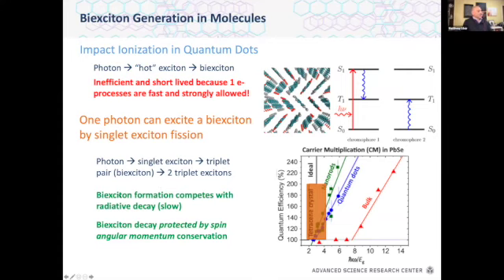So here, instead of Biexciton formation having to compete with carrier cooling, it has to only compete with some sort of decay back to the ground state. And so we're photoexciting a cooled singlet exciton. So again, carrier cooling, it's already cooled in the sense of it's not easily able to relax to any low-lying triplet level. So, we'll have 1 nanosecond or 10 nanosecond decay times back to the ground state. And so we have basically 4 orders of magnitude longer to form our Biexcitons. And in addition, what we'll see is that the Biexciton decay is protected by spin angular momentum. And so instead of having 100 picosecond rates, we'll have time constants of up to something like a microsecond.